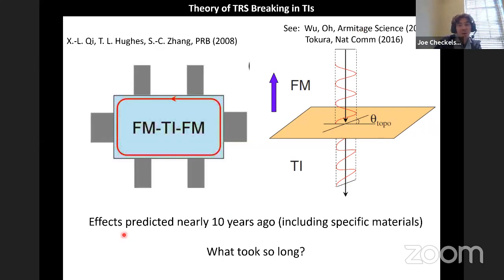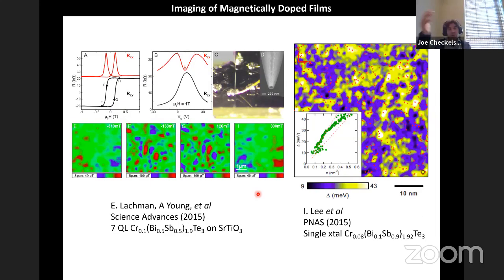So one way of posing from a materials view is, what took so long? Right? Why was it so difficult for us to achieve these effects? And that question was largely answered when our friends with the real space scanning techniques came and started examining these materials. So this is an example of two different scanning techniques on two different kinds of magnetic topological insulators. This is pretty much the same as the original material in which the quantum anomalous Hall effect was discovered. So you're putting chromium into a thin film of bismuth antimony telluride.